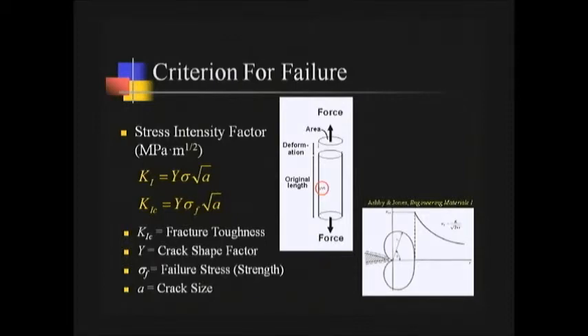And you can calculate the stress intensity factor by multiplying the far field stress that is all over the material times the square root of A. A is the flaw size. So this is the size of the crack that's going to be growing into the material. And Y is a factor that tells us the shape of the flaw and the location of the flaw.